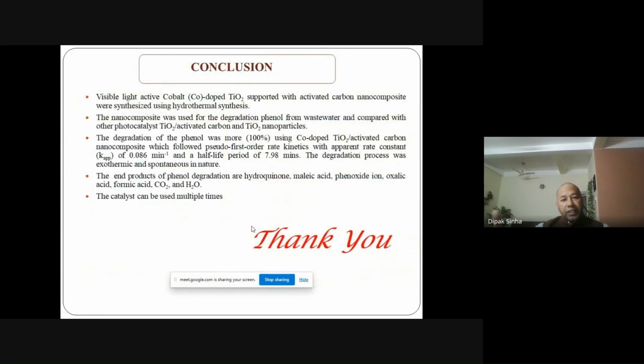In conclusion, I can say that by doping cobalt metal into titanium dioxide, we could shift the photocatalytic degradation from the UV region to the visible region. We developed a nanocomposite by putting this titanium dioxide doped with cobalt metal onto a carbon surface, and that is how the efficiency of the photocatalyst increases, because the carbon surface gives more surface area, which helps adsorption of more pollutant, and ultimately leads to better photocatalytic performance of the catalyst we have used.